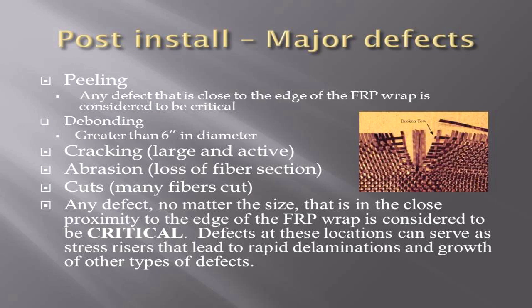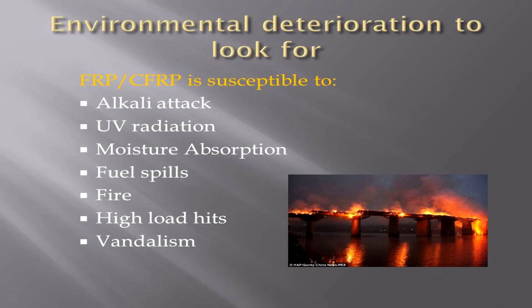Cracking large and active, abrasion where you've actually lost fiber sections, cuts where many fibers are cut, and any defect, no matter the size, that is in close proximity to the edge of the FRP wrap is considered to be critical. Defects in these locations can serve as stress risers that lead to rapid delaminations and growth. In addition to that, carbon fiber is susceptible to alkali attack, UV deterioration, moisture absorption, high impact loads, vandalism. So it's a delicate creature.